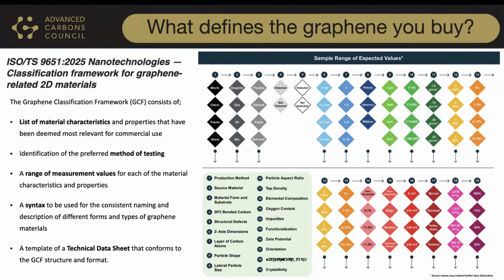Now, from the image on the right, when you look at the breadth of parameters, you see production method, layer number, lateral size, zeta potential, crystallinity, etc. Now, these are 19 distinct characteristics that together define performance. And because graphene performance is multidimensional, you cannot reduce it to a single number, not surface area, not purity, not even price per kilo. So this framework allows producers to report consistently, and it allows buyers to compare the materials transparently. And ultimately, this is what can enable industrial adoption at scale.